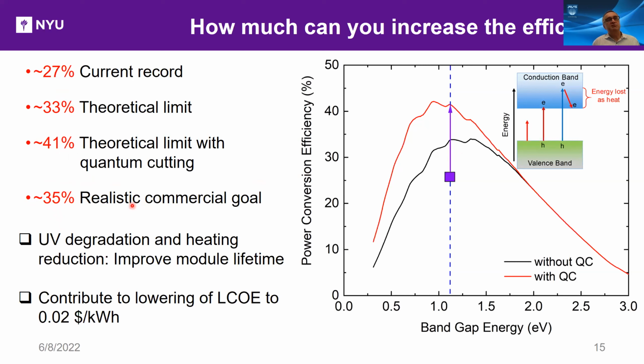Perhaps more important than efficiency, and this was pointed out to me, is the UV degradation and heating reduction that comes with taking all those UV and blue photons and putting them in the infrared. That could improve degradation and improve module lifetime. And from the plot on how to get to a 2-cent levelized cost of energy that SETO had, this also has a significant effect. So both of these will contribute to lowering the levelized cost of electricity.